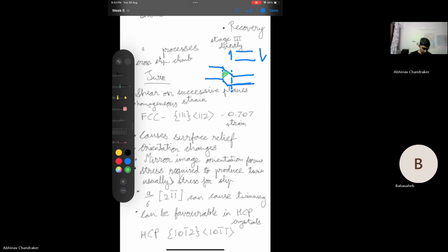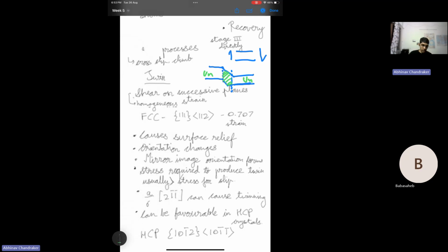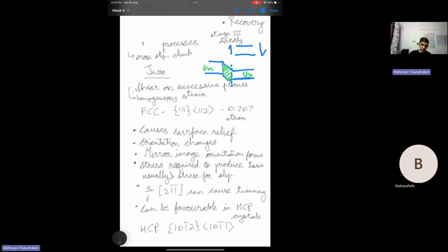This is the twin. These both are untwinned. This is different from slip. In slip, you just have dislocations which are moving on different slip planes and leading to overall formation of slip steps in the material. And there you have lattice translations whenever a particular slip event is occurring. But here you are having a uniform value of shear strain in the material when twinning is occurring.